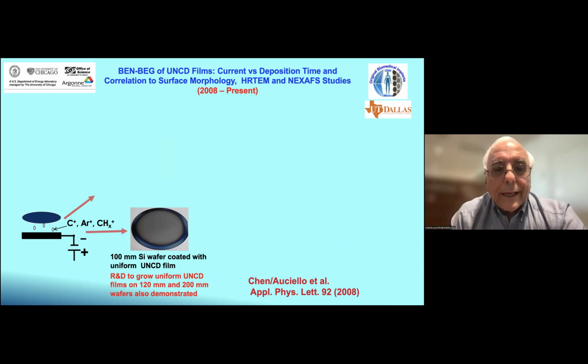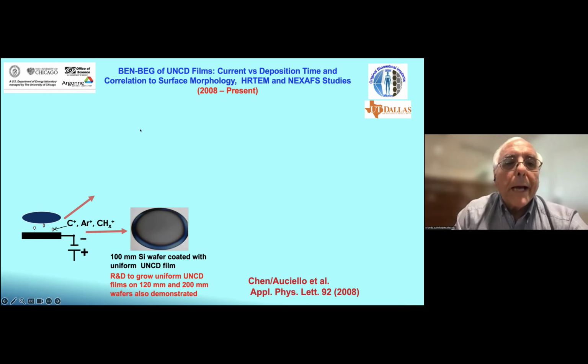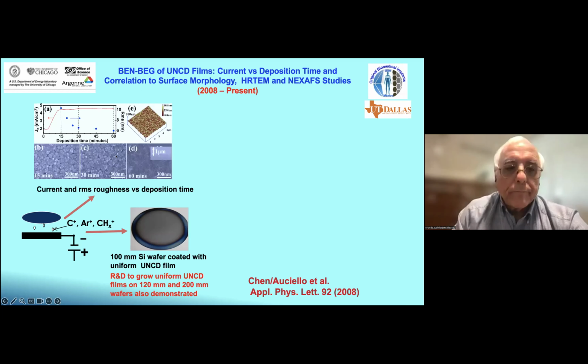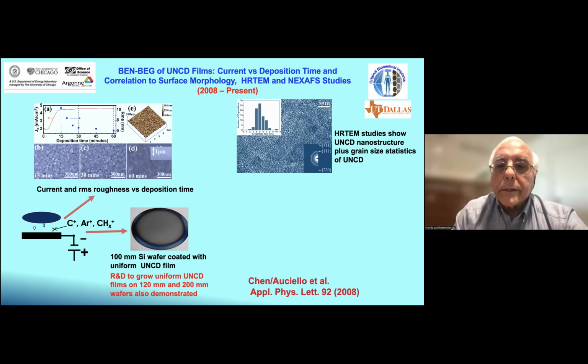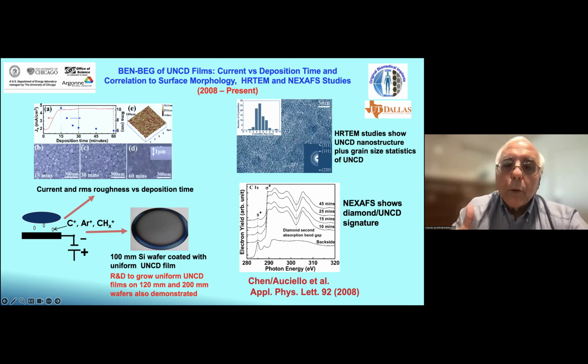Now, I am very interested in continuing reducing the cost, and the seeding process takes 1 hour, which contributes to the cost. So what we developed in the last 5 years is a process that we call bias-enhanced nucleation, bias-enhanced growth. So if we put semiconductors or metallic substrates and we apply a negative voltage with respect to a positive electrode on the top, we can accelerate the carbon plus, argon plus, CHx plus ions that implant on the surface and nucleate the film. And with this process, we can grow exactly the same UNCD films as we were growing with the seeding process. Here we see the high resolution TEM on the top, and at the bottom, the NEXAFS to confirm that our UNCD doesn't have the graphitic phase.